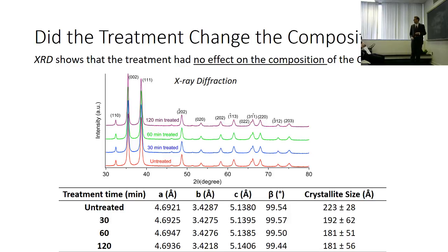Not very nice in my case, because they all look the same, so I'm not changing the composition. Everything was very much alike. You can tell because the intensities and the locations of these peaks are in the same place. That means it's the same material, basically.